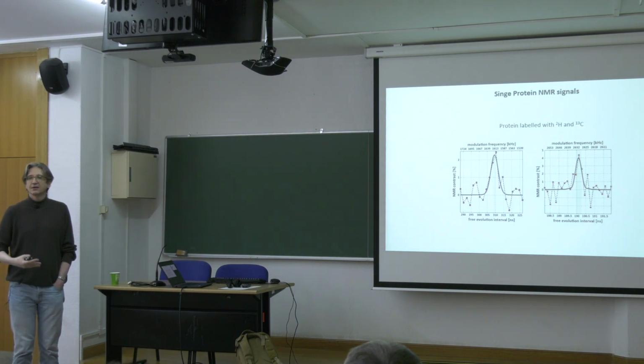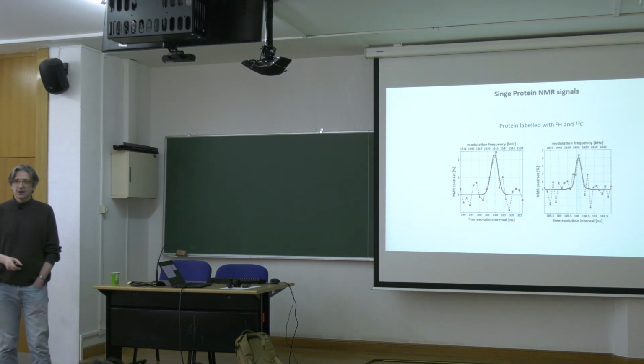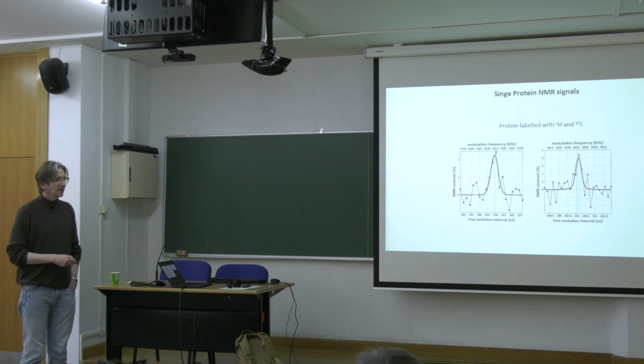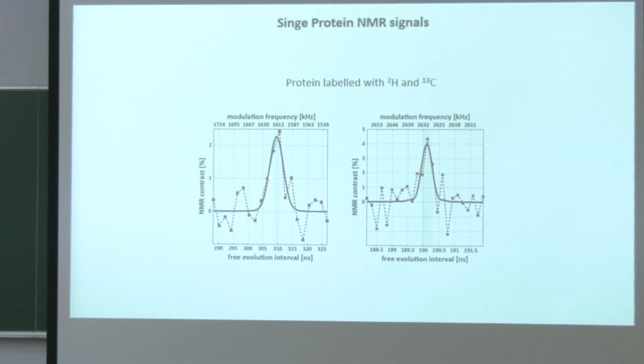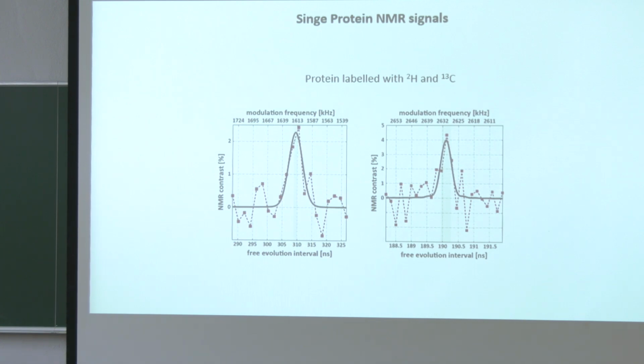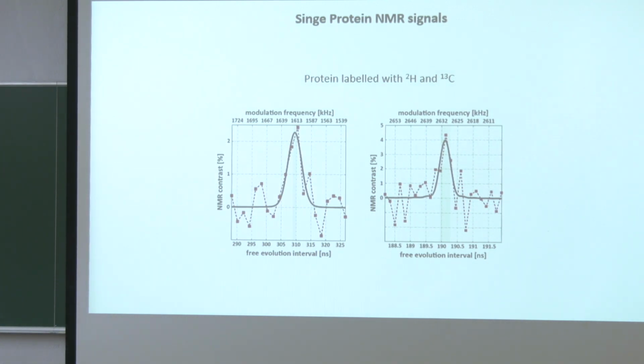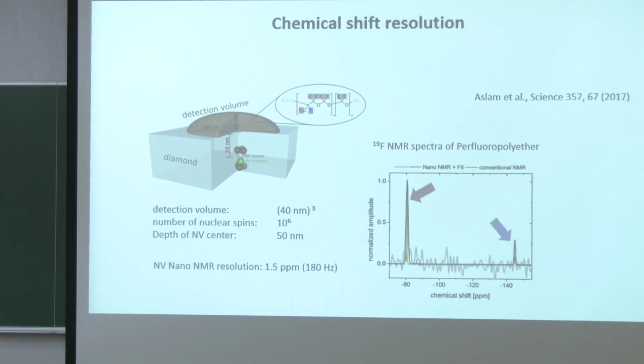Just to give you a sense of what the improvement is compared to the state of the art: a typical nuclear magnetic resonance experiment is done on billions of molecules. So here, by approaching a sensor to a single molecule, you gain orders of magnitude in sensitivity. However, you see that the spectra are noisy, although they've been acquired for tens of minutes. And the line width, which is related to the time interval between pulses, is not very sharp. It is not yet good enough, this experiment, to answer the question about the structure and dynamics of the molecule.